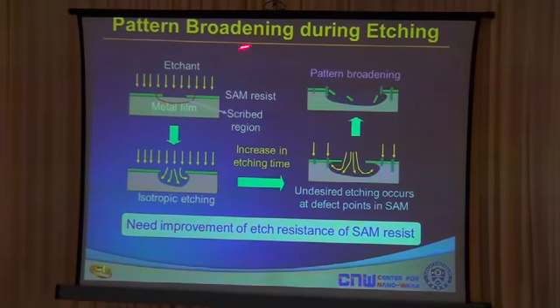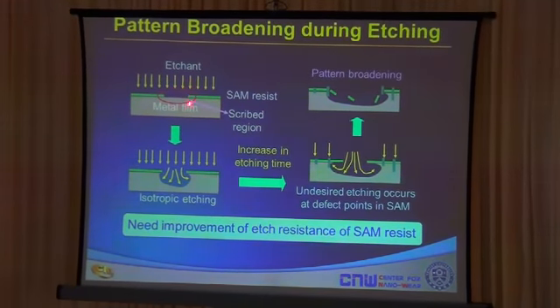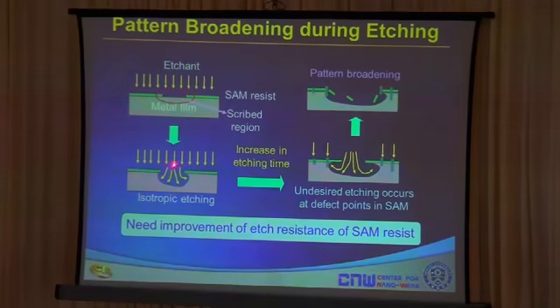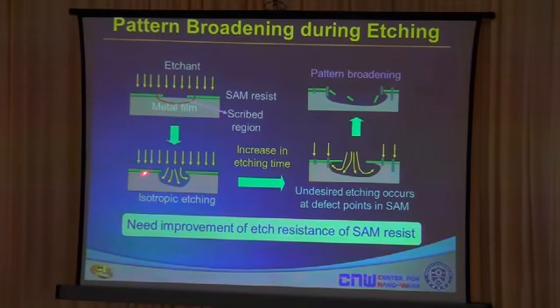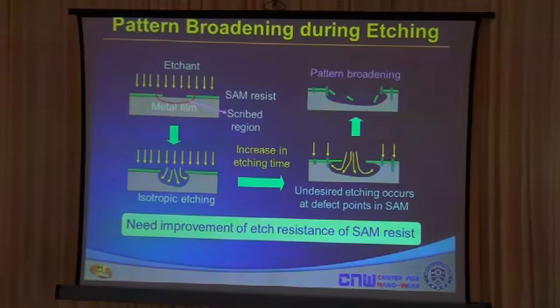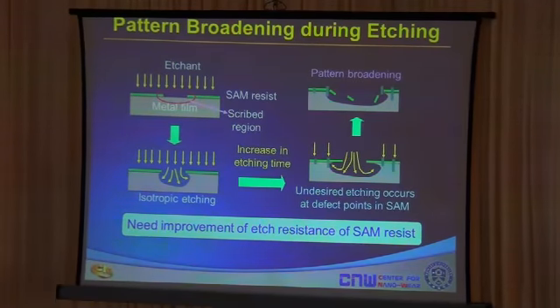This is because we're not able to optimize the etching process, and we face the problem of pattern broadening during etching. This is the SAM resist, and this is the part where we removed it by mechanical action. When we etch the surface, the etchant will penetrate below the resist area and can lead to some failures in the resist area, ultimately creating a width that is larger than the initially scribed mechanical region. So we need further optimization in this regard to make sure that the width would be equivalent to the tip size that we use.